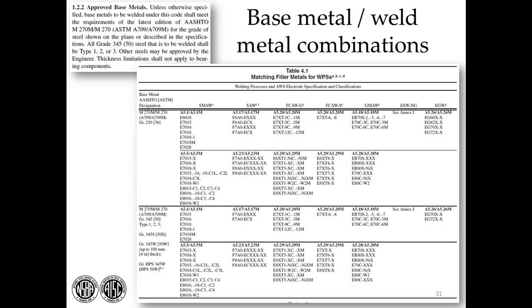One of the characteristics of these consumables is that they are intended for, I'm going to say, "low hydrogen" situations. I say that in quotes because we talk about low hydrogen as a practice, and we use that term in our codes, but there isn't an official designator that says at this level of hydrogen you're low, and above that you no longer are. Now there are some low hydrogen designators for stick electrodes, but for most electrodes you won't get a low hydrogen designator. So the best practice is to simply use these classifications under D1.5. And more simply, if you're in a situation where you're concerned, say fabricate and weld to D1.5, and then you don't have to be concerned about either the consumable chosen or the practices used in association with those consumables.